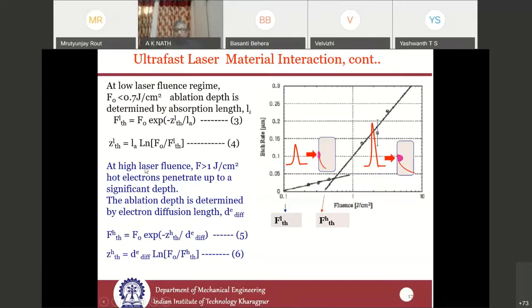So the expressions remain the same. Only thing is that we now have a different threshold for high intensity ablation compared to low intensity ablation. So based on these experimental results, people have tried to theoretically model and find out, for a given laser fluence, what is the depth up to which material is going to get ablated.